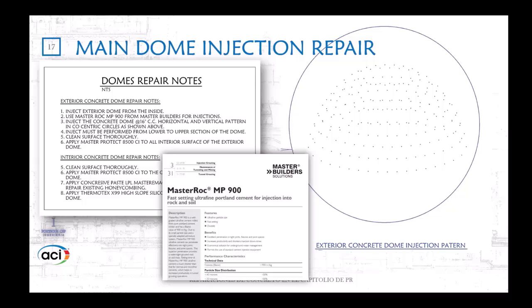So thanks to the support of Master Builders at that time, now Sika, they recommended a micro cement to inject from the inside. It's a micro cement used to stabilize tunnels inside mines. So, following the diagram on the right, we injected every 16 inches in circles from the bottom up, always from the bottom up. Low pressure injection, only 30 psi. We just want to fill the voids, and the contractor has to watch that there is no micro cement on the outside to damage the marble. It happened, I think, 5 times that the micro cement injection went outside.